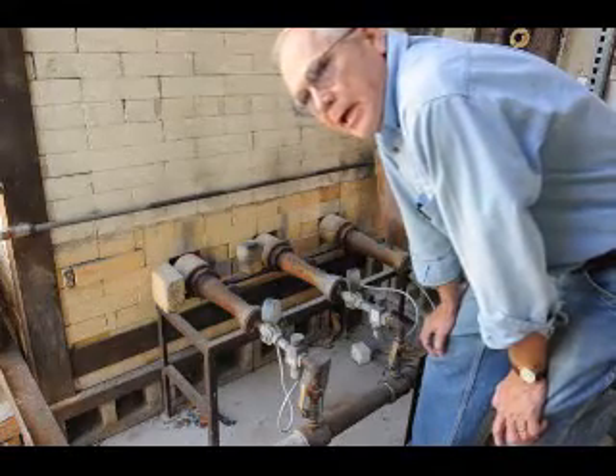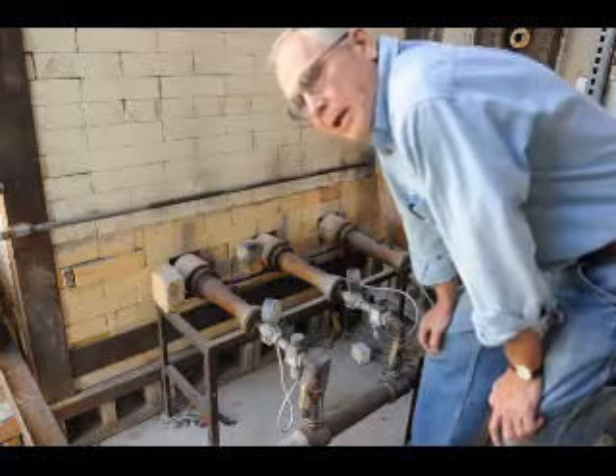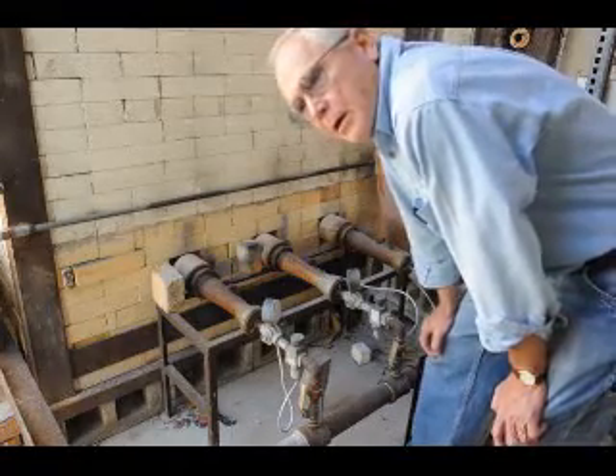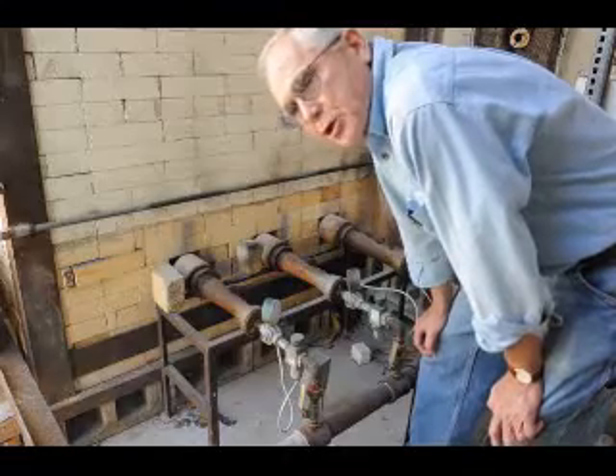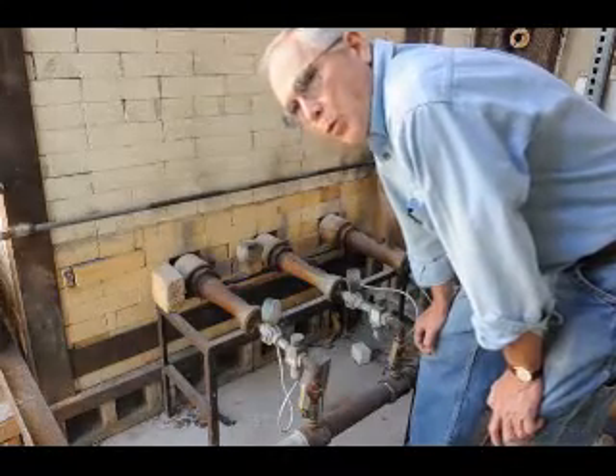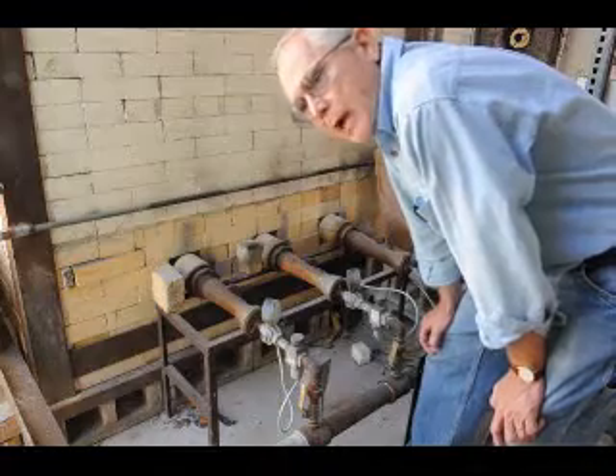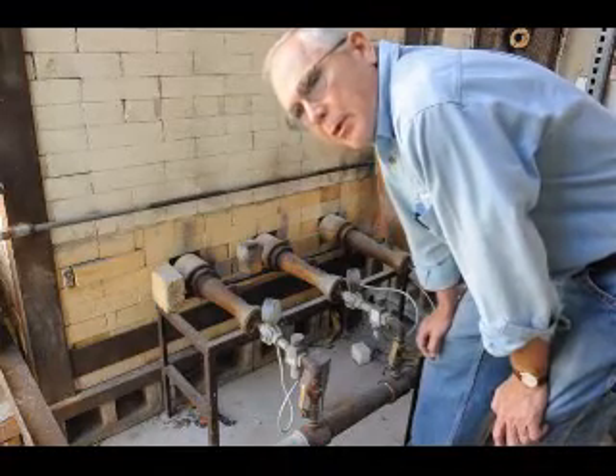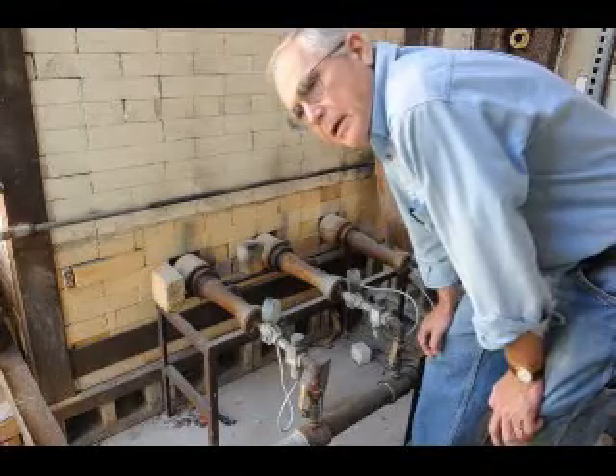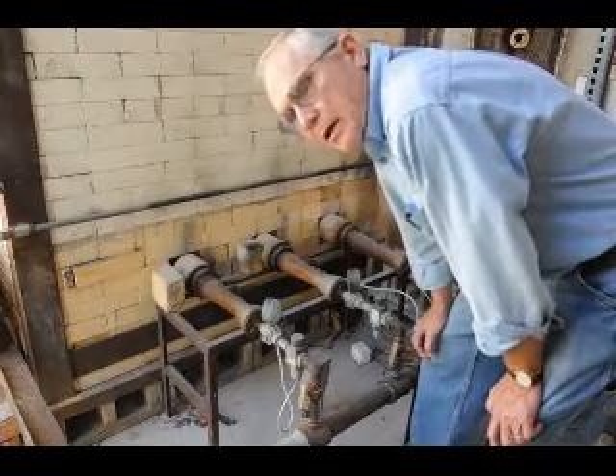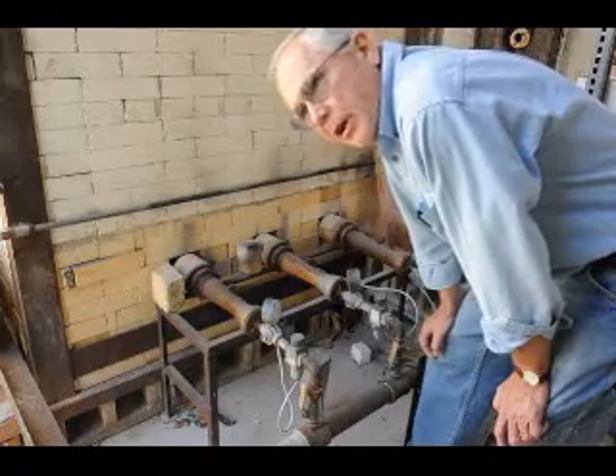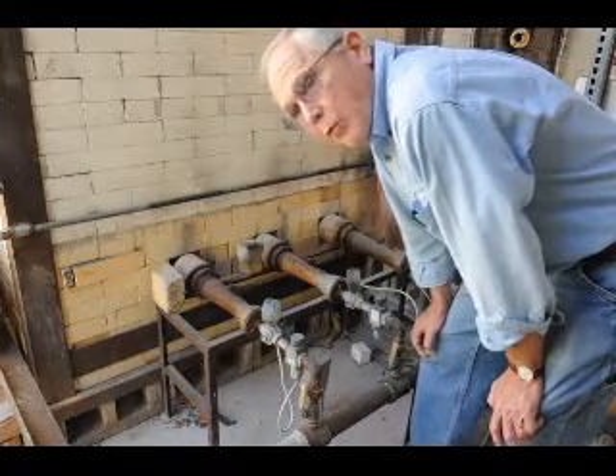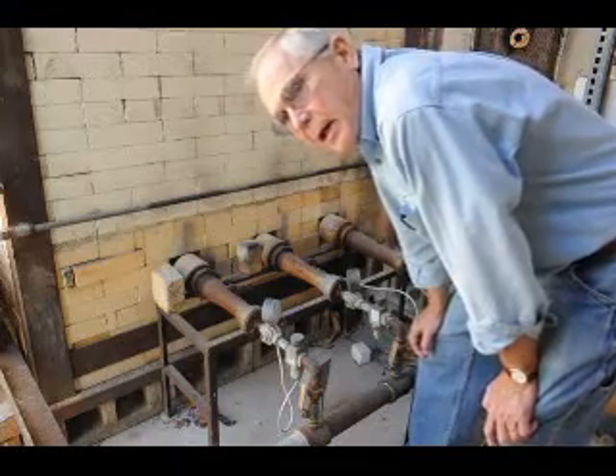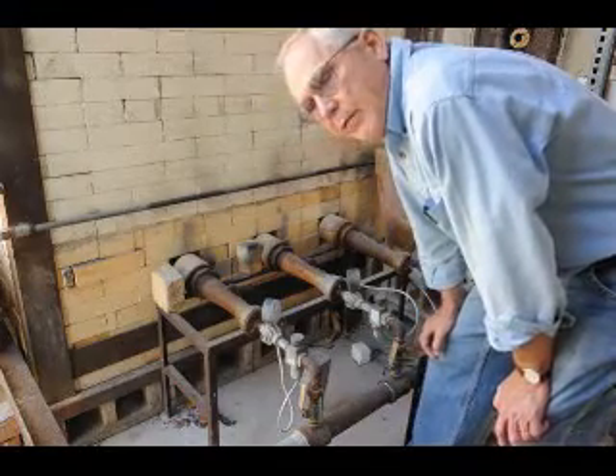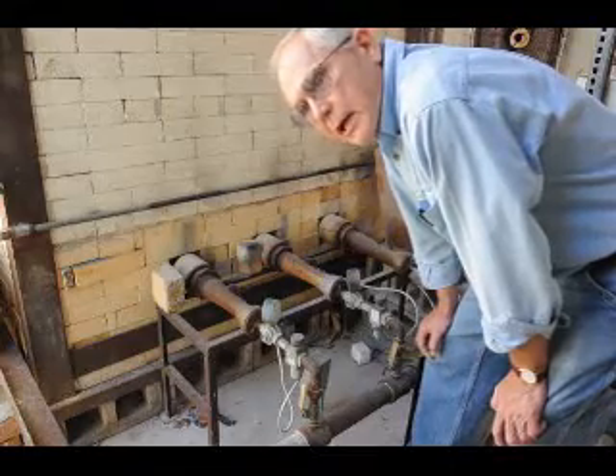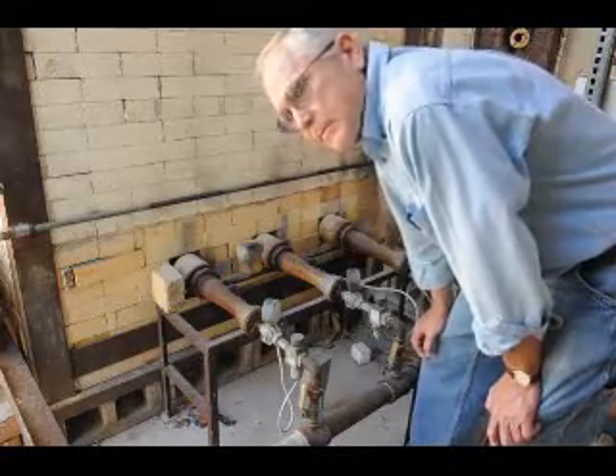Since everything is already dry in the kiln, but everything's not already dry, because the clay balls that I use to put on the top of the stilts, between the stilt and the shelf, that's still wet clay. And if the temperature rises too rapidly, then I worry that those clay balls will explode and get clay in my pieces. Since I've started firing this way, the problem that I had before has essentially gone away. I have almost no loss of pots based on those getting clay particles in the pots.